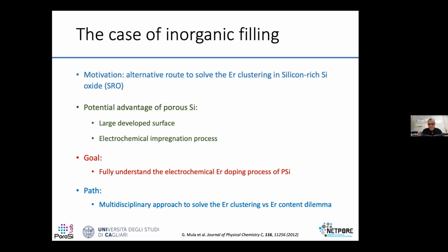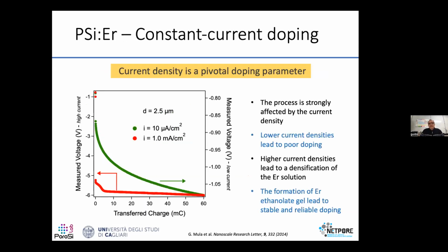The first thing you notice is that when you do constant current doping on porous silicon with erbium, the current density becomes a pivotal doping parameter by itself. So if you measure the current density as related to the inner surface of the pores, then you notice that for low current densities, you have a single process, which is described here by the behavior of the voltage versus the transferred charge in green. You have a single transient, which is what you expect for a normal deposition by an electrochemical process.